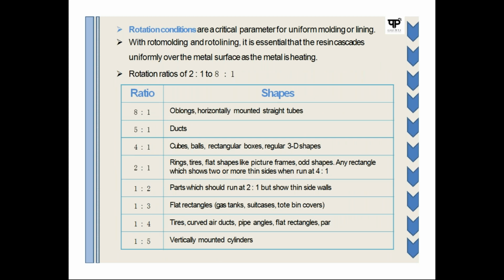Now, as far as processing is concerned, you can see the different shapes, the ratio of the major and minor axis rotations are very important, because in most cases of rotomolding, 4:1 is used. But depending on the shape of your product, you have to change the ratio between the major and minor axis, because it is going to play a vital role in dispersing this material uniformly throughout the mold surface. So that factor is involved in fixing that particular ratio.